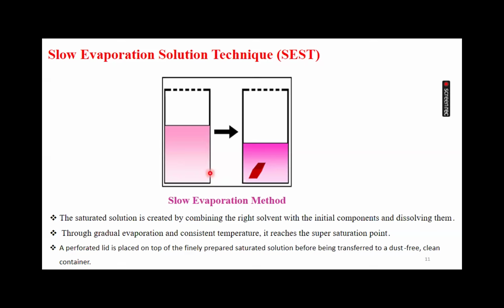Despite all these drawbacks, this is a practical and simple approach for generating large, high-quality single crystals. The only way to produce organic crystals with low melting point, quick decomposition rate, and low temperature coefficients of stability is by this technique. Slow evaporation solution technique, some advantages and some disadvantages.